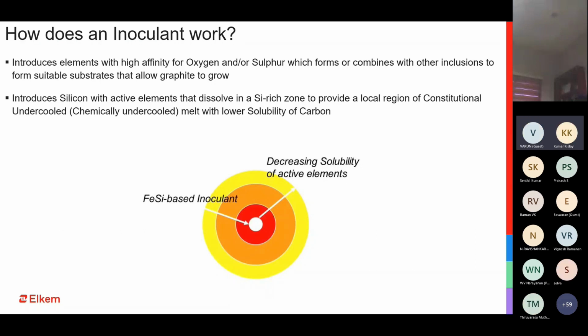Now, why is it only ferrosilicon based? So that can be another question. Why can't we add pure strontium? Why can't we add pure barium or pure calcium into the system? So why a silicon based one? Why a ferrosilicon based inoculant? So this silicon which comes with your inoculant, which can be in the range of 50 to 75%, this silicon coming in with your inoculant creates a small zone which is rich in silicon.